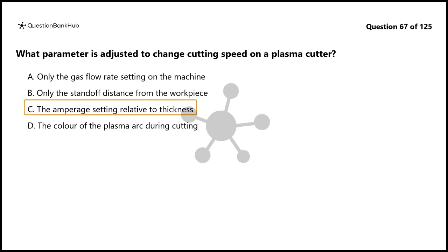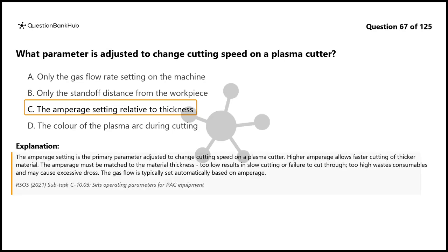The correct answer is C. The amperage setting relative to thickness. The amperage setting is the primary parameter adjusted to change cutting speed on a plasma cutter. Higher amperage allows faster cutting of thicker material. The amperage must be matched to the material thickness. Too low results in slow cutting or failure to cut through. Too high wastes consumables and may cause excessive dross. The gas flow is typically set automatically based on amperage.